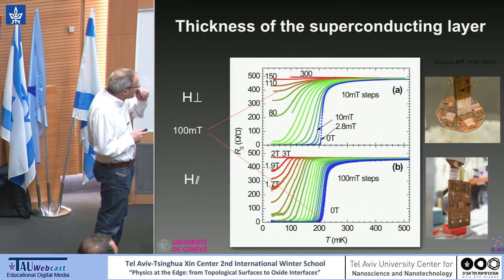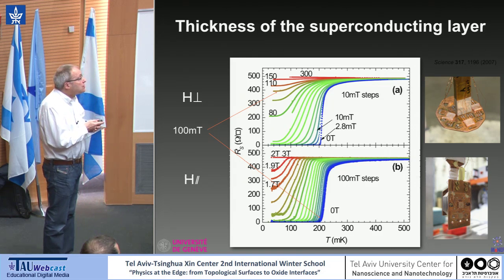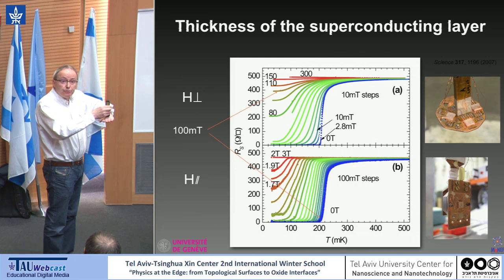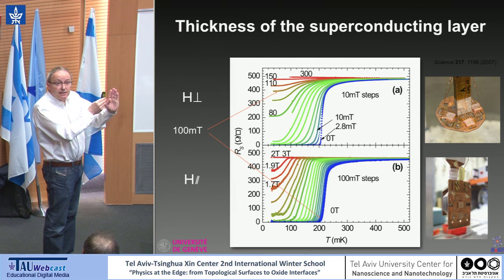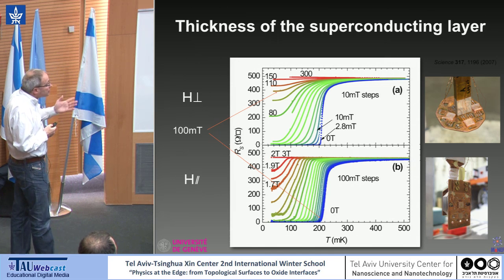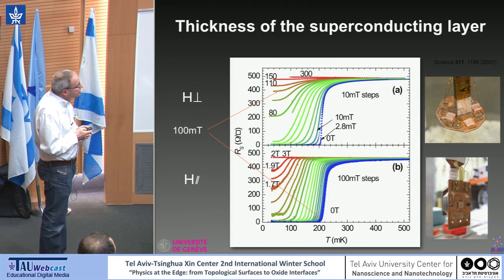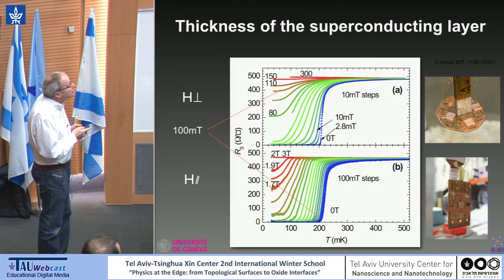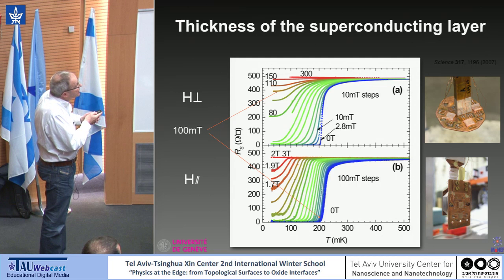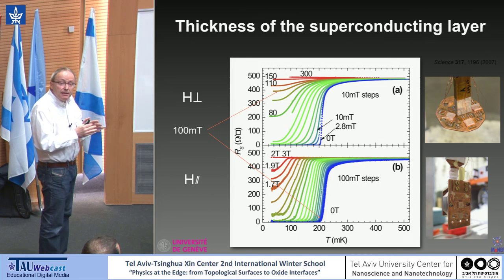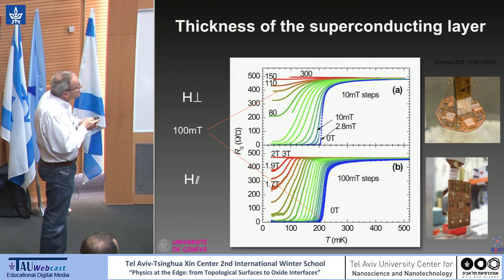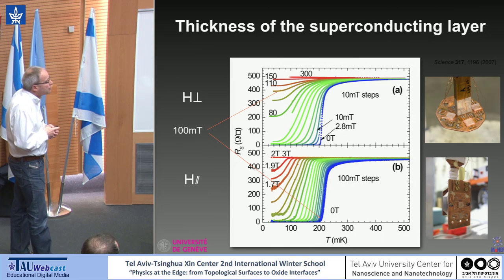So what we do, we measure the superconducting transitions in perpendicular and in parallel fields. Once the field is perpendicular to the interface, and in the other case, it is parallel to the interface. And you see here the transitions. This is the perpendicular direction, parallel direction. It looks very similar, but in fact there is a large anisotropy. You see here that 100 millitesla is nearly suppressing superconductivity. In the parallel case, 100 millitesla does not do very much, and you need maybe 2 Tesla to destroy superconductivity.